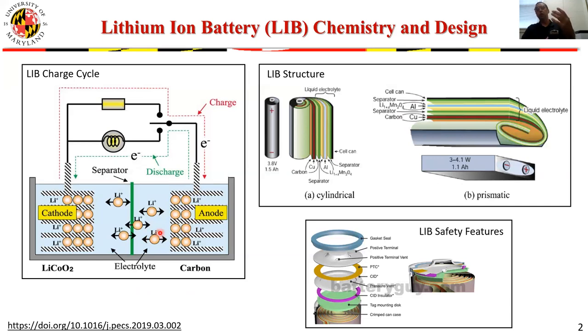When you remove the charging potential and instead connect it to the load, the reverse process takes place. The reason the reverse process takes place, in principle, is because those lithium atoms much prefer to be combined with oxygen in the cathode. So it's much more thermodynamically favorable for them to be chemically bound with this oxygen. This oxygen is very electronegative and lithium is very electropositive, and they really like each other.